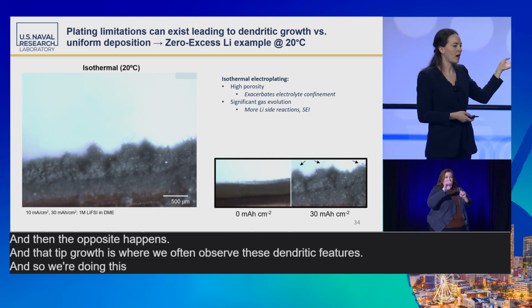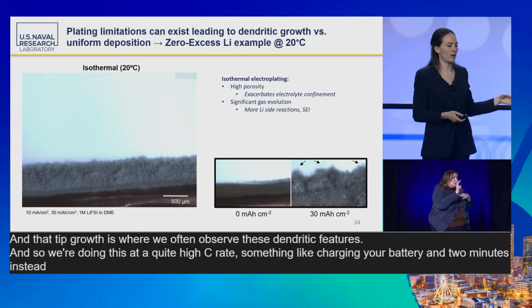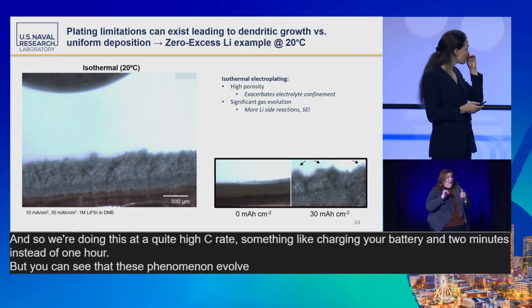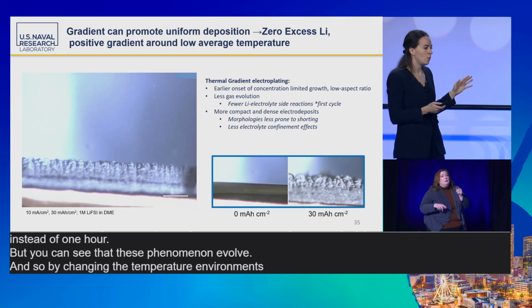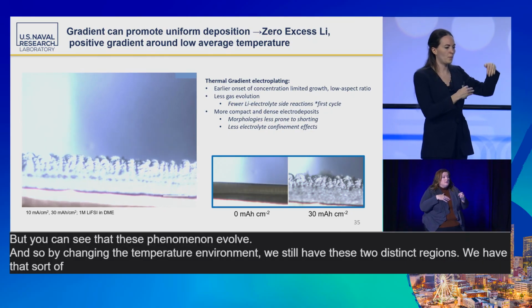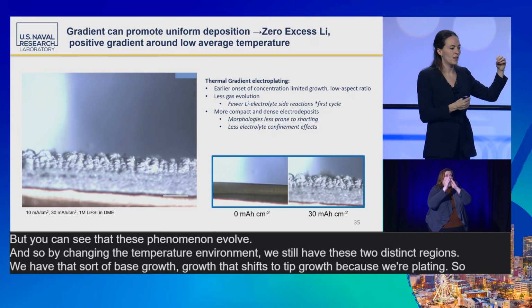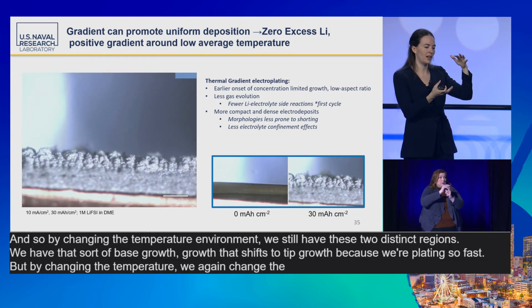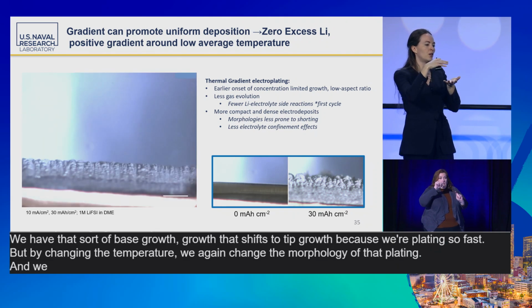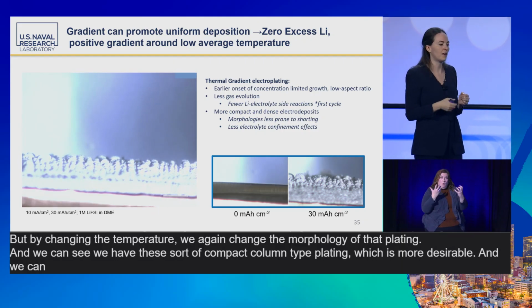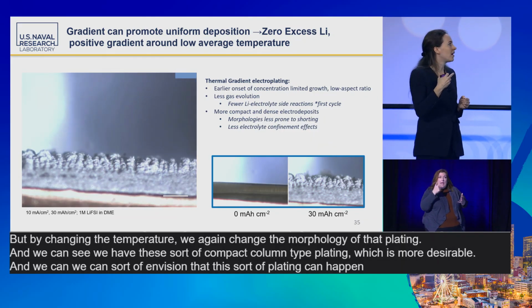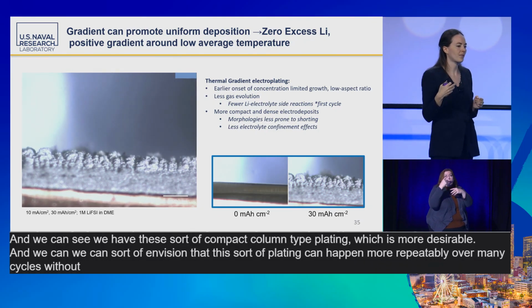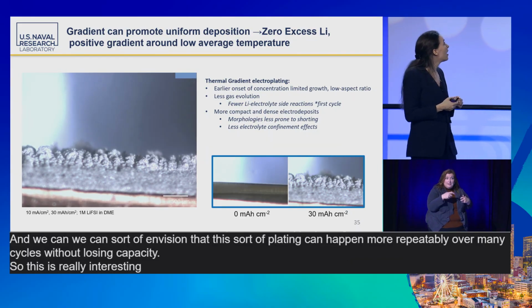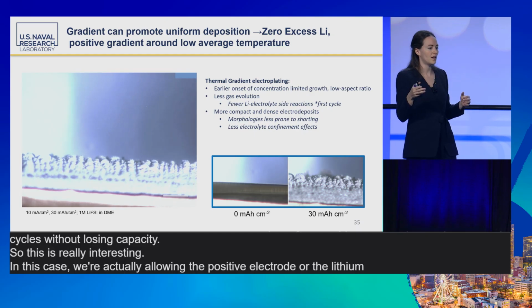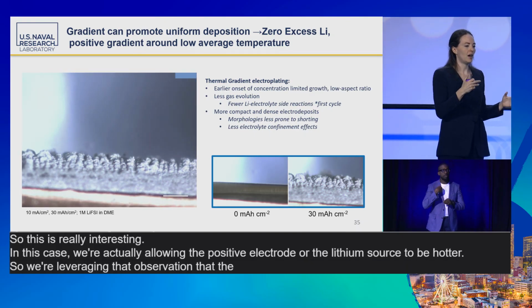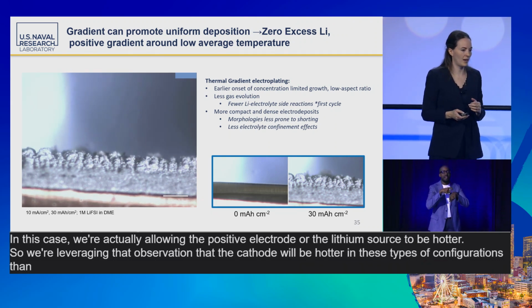We're doing this at quite a high C rate, something like charging your battery in 2 minutes instead of 1 hour. But you can see that these phenomena evolve. By changing the temperature environment, we still have these two distinct regions. We have that base growth that shifts to tip growth because we're plating so fast. But by changing the temperature, we again change the morphology of that plating. We can see we have this compact columnar type plating, which is more desirable. We can envision that this sort of plating can happen more repeatably over many cycles without losing capacity. So this is really interesting. In this case, we're actually allowing the positive electrode, or the lithium source, to be hotter. So we're leveraging that observation that the cathode will be hotter in these types of configurations than in lithium-ion batteries.